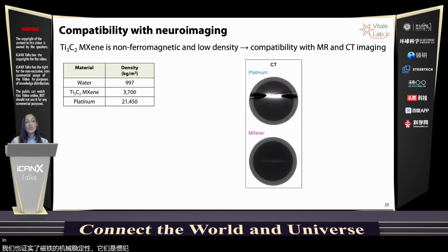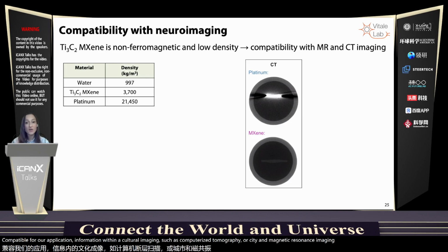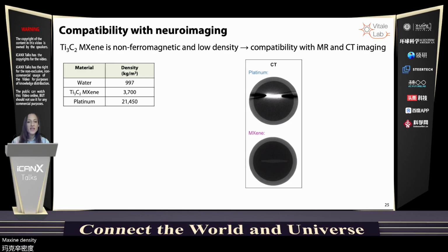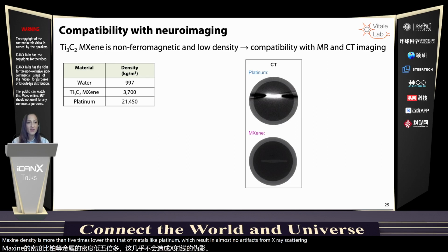In addition to the favorable electrochemical behavior, the physical properties of MXene make it ideally compatible for application in conjunction with clinical neuroimaging, such as computerized tomography or CT and magnetic resonance imaging or MRI. MXene density is more than 5 times lower than that of metals like platinum, which results in almost no artifact from X-ray scattering when these devices are imaged in the CT scan.